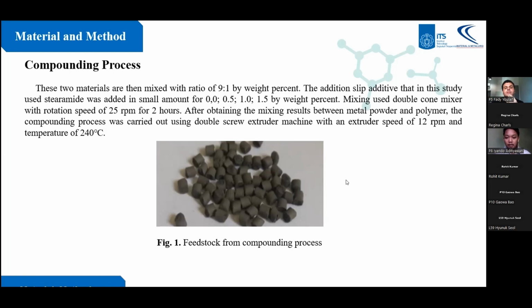After obtaining the compounding, the metal powder and polymer were processed using a double screw extruder with an extruder speed of 12 rpm and a temperature of 240 degrees Celsius. And the picture explains the feedstock of material from the compounding process.